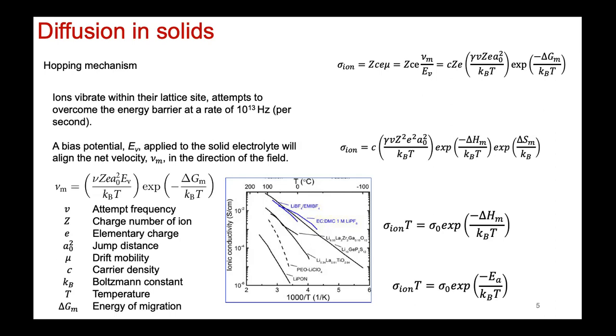So in the end, you get a plot that looks like this, and this is what we've been talking about: 1 molar LiPF6 in EC/DMC. What we have to beat is basically 10 millisiemens per centimeter. That is the number we have to beat in designing a solid electrolyte that has comparable ionic conductivity at room temperature to that of liquid electrolyte. So 10 millisiemens per centimeter. More like 5 is good enough, but 10 will surpass it.